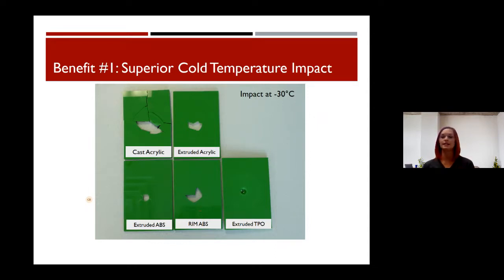So the first one, like I said, this is a major selling point for TPO, cold temperature impact. You can see these samples. They were put down in a freezer at -30°C. You've got 2 different types of acrylic and then 2 different types of ABS compared to the TPO. You can see they've all cracked except for the TPO. It's definitely denting, but it's not full failure. So that's one of the major benefits.